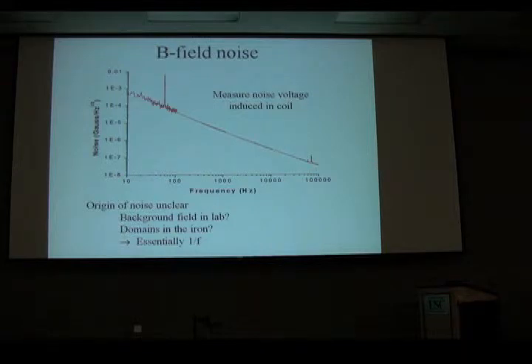So what we did then was we looked at what kind of magnetic field noise. So the cavity, sometimes you want to modulate your magnetic field so it has a coil built in there. So we can measure the voltage coming back out that coil, out of the modulation coils. And if you look at the noise you get, you get very nice one over f noise. I had originally thought that it was all kinds of noise around the lab. This is a spur at 60 hertz, but in fact integrated that has almost no weight under it. It's all this one over f noise.